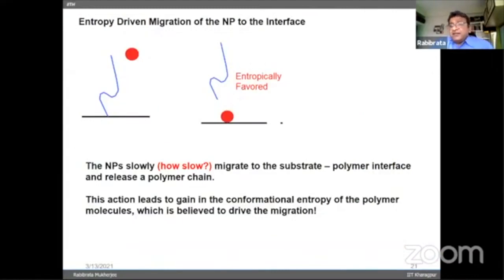So the main reason which is considered for the stabilization of these films is, it is argued, largely an argument, largely a speculation, that these particles actually migrate to the free surface. And why do the particles migrate to the free surface during annealing? It might be enthalpic, where the thermodynamics is based on the surface energy of the particle, the polymer, the surface, but more importantly, the entropic contributions come into play.